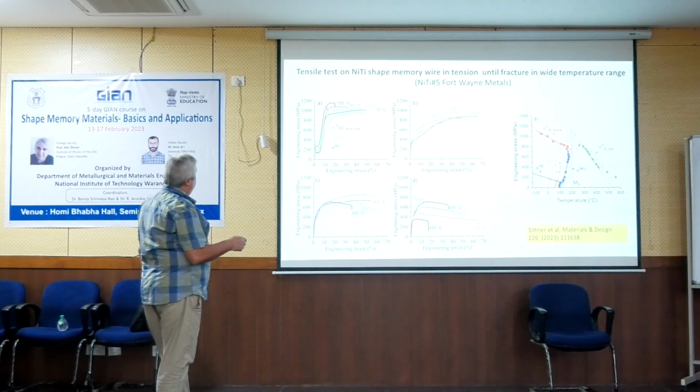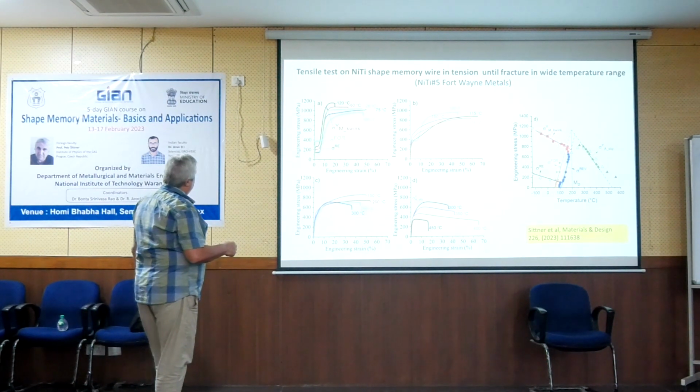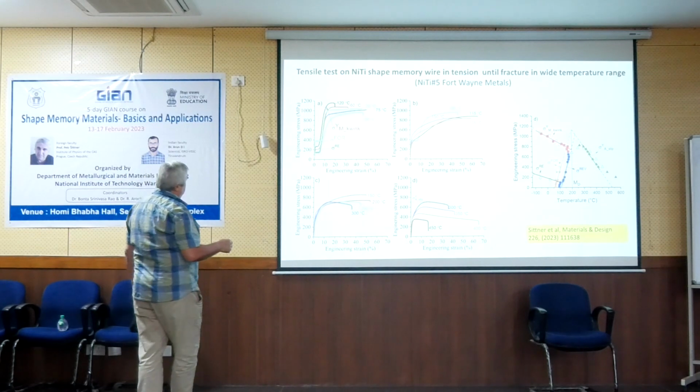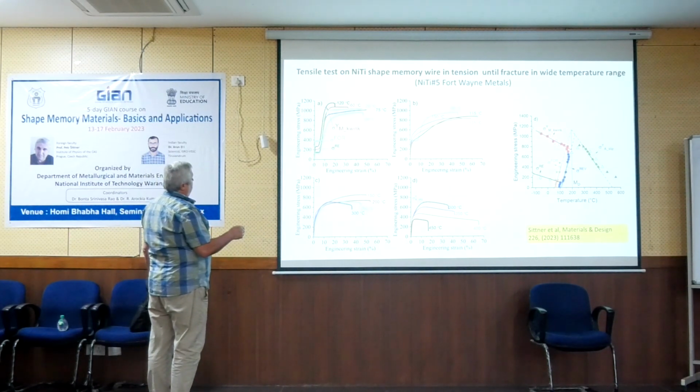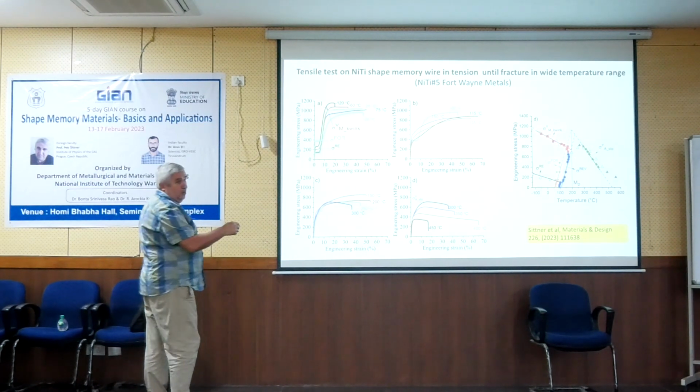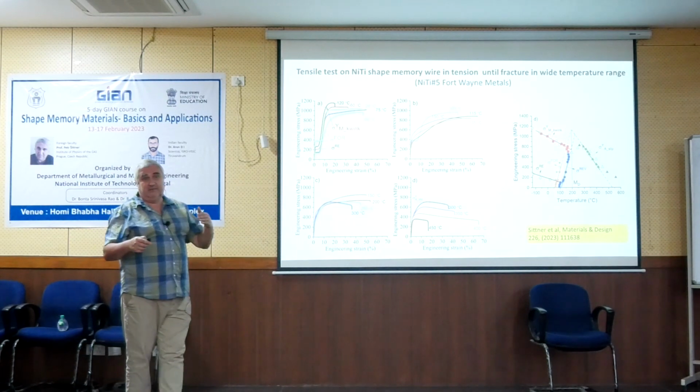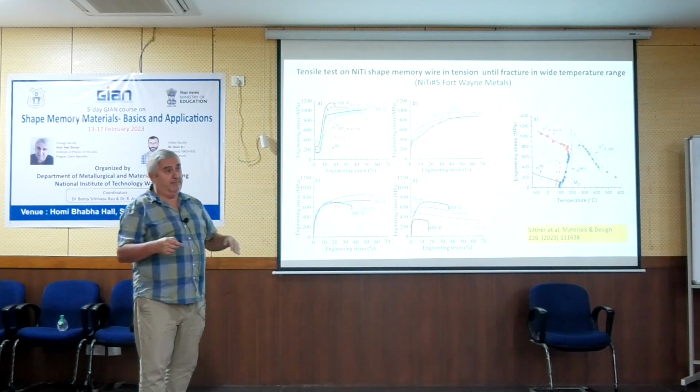Yesterday, when we looked at it, it was at room temperature, like this green one. So you see the green curve. This is the curve which we approximately measured yesterday in the laboratory test. So there is a reorientation, around 6%, and then around 1 gigapascal there is a flow. Exactly, yesterday in the test we had the plastic flow at 1 gigapascal.